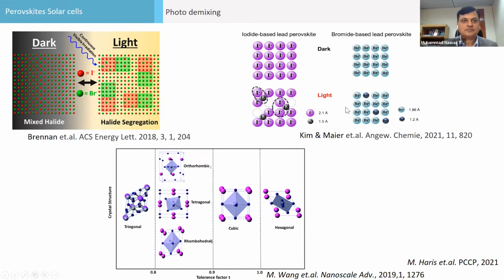Similarly, there was a very good paper with Joachim Maier, and there is a demixing of ions. They also studied the same. There is a demixing of ions, and they call it photo demixing, because in the light they demix and the devices are not good. And if you look at the tolerance factor here, the tolerance factor is close to 1, which means this perovskite is more stable. And formamidinium is the case now, which was not the case with methylammonium and other types of perovskite.